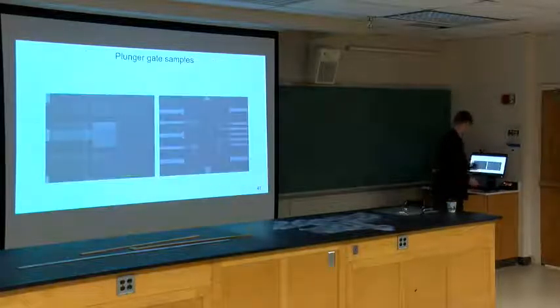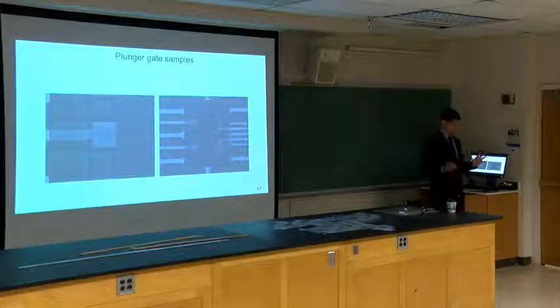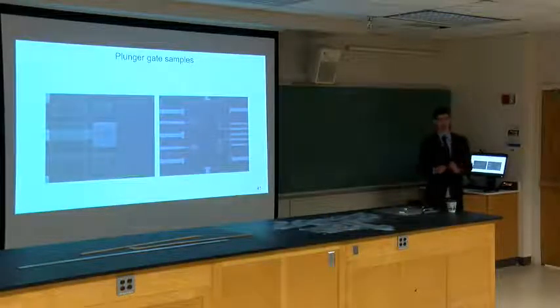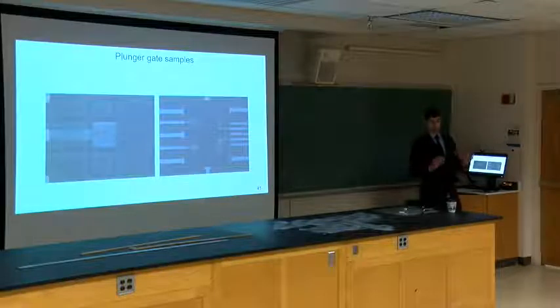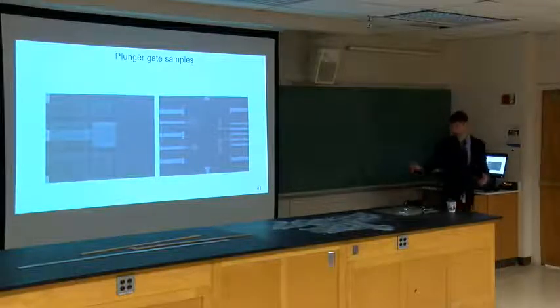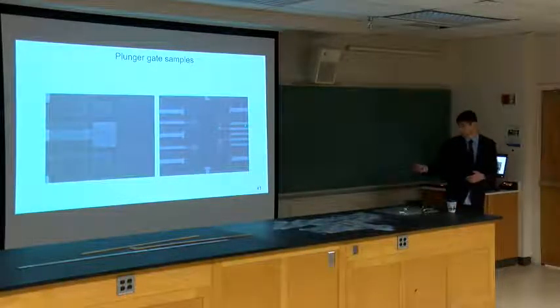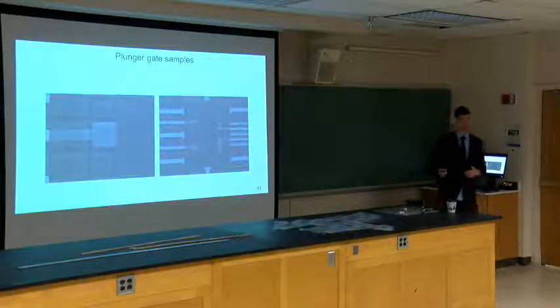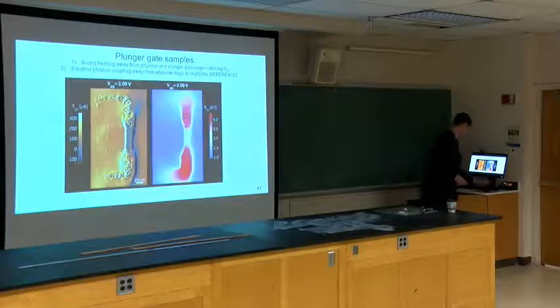We still weren't sure what was going on. So one of the ideas was, well, let's control the electrostatics at the edge better than just having a blind edge. So what we did was made samples that have plunger gates underneath sections of the graphene, and then so we can control the electric field there much more clearly.